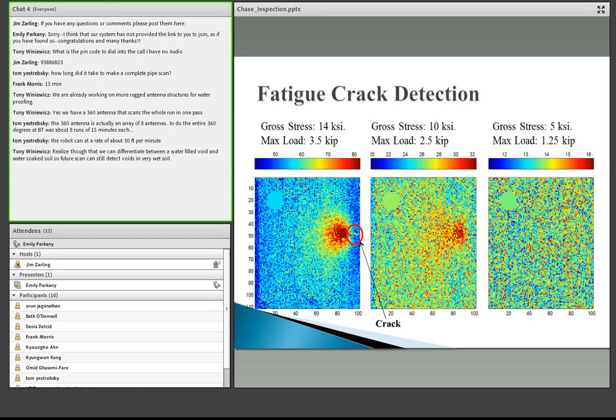Using this capability, we tested our ability to detect a fatigue crack based upon the fact that if a crack is present and it is being subjected to a dynamic loading, the stress at the tip of that crack is very high and is producing a thermoelastic signal that our system can detect. So you can go out with this system and take images and determine whether or not a fatigue crack exists and whether or not the fatigue crack is experiencing sufficient stress to be in a growing state.